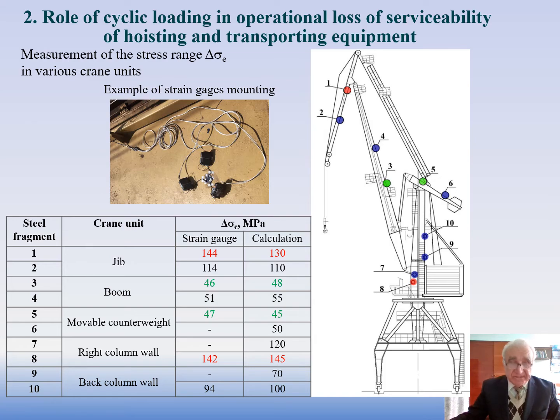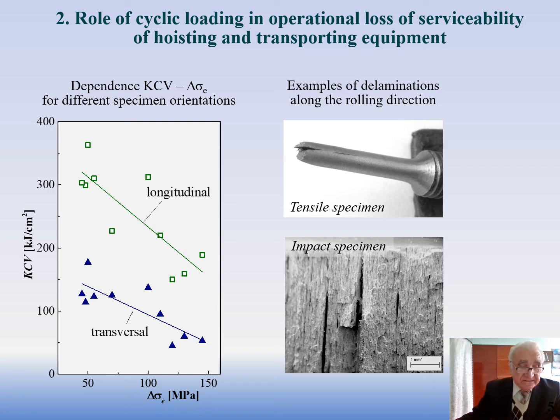This made it possible to evaluate cyclic loading, stress, and most importantly, the difference in their levels for the test crane units. As expected, the value of cyclic stresses to which the crane components were subjected contributed significantly to the intensity of degradation process in them. A comparative assessment of in-service stresses and the corresponding resistance to brittle fracture for each unit is presented in this table. A relationship between the obtained values of stress range and impact toughness has been established. The higher the stress level, the lower the resistance to brittle fracture.